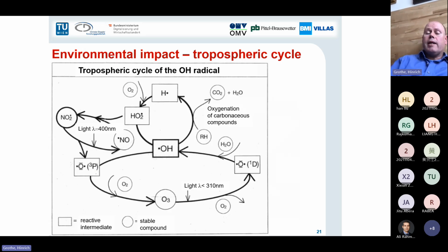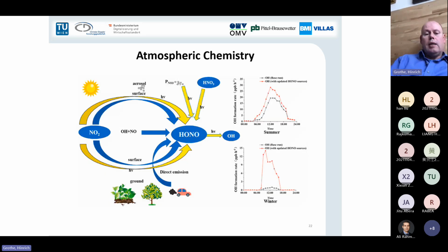And to generate these electronic excited oxygen atoms, you need light below 310 nanometers. So you need near UV light, and this is important to run the whole chemistry, the whole tropospheric cycle of the OH radical. And this, of course, is very important also for the oxidation of our bitumen. In general, NO2 then reacts with OH radicals, and finally on a surface, like our bitumen surface, like the road surface, but also many building surfaces, you have the formation of HONO, which is an important intermediate.